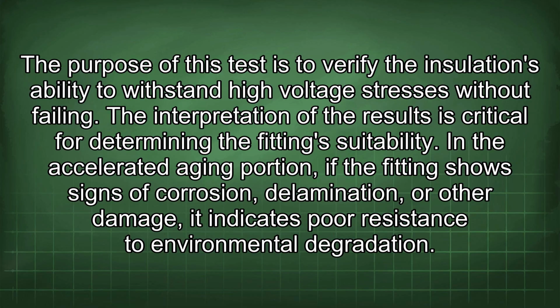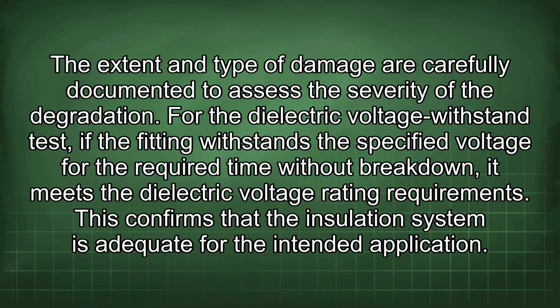The interpretation of the results is critical for determining the fitting's suitability. In the accelerated aging portion, if the fitting shows signs of corrosion, delamination, or other damage, it indicates poor resistance to environmental degradation. The extent and type of damage are carefully documented to assess the severity of the degradation. For the dielectric voltage withstand test, if the fitting withstands the specified voltage for the required time without breakdown, it meets the dielectric voltage rating requirements. This confirms that the insulation system is adequate for the intended application.